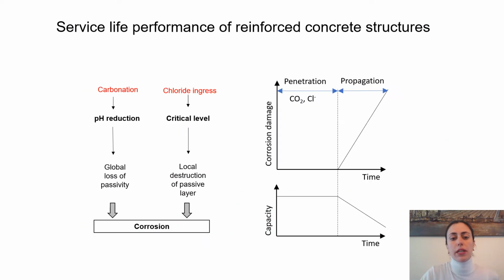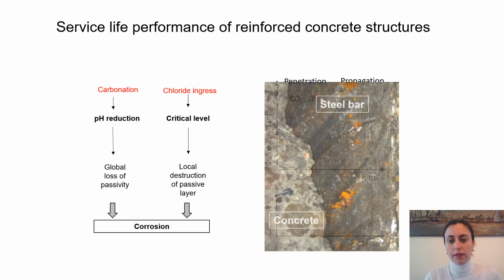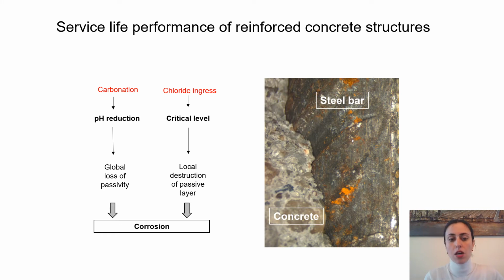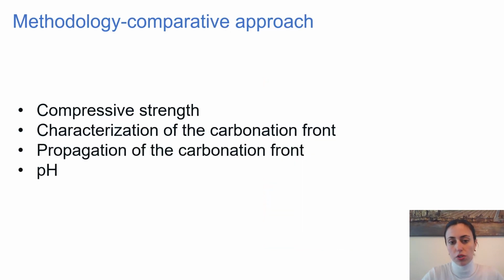In this presentation, I will mainly talk about carbonation in terms of service life performance. There are two main degradation mechanisms, let's say major ones, when it comes to the end of the service life of the concrete, and those are carbonation and chloride ingress. We are interested today only in carbonation, and as you can see, carbonation mainly leads to pH reduction and to the global loss of passivity of the steel reinforcement in concrete. However, is this the case also in alkali activated concrete? So this is what is known for cement-based concrete.